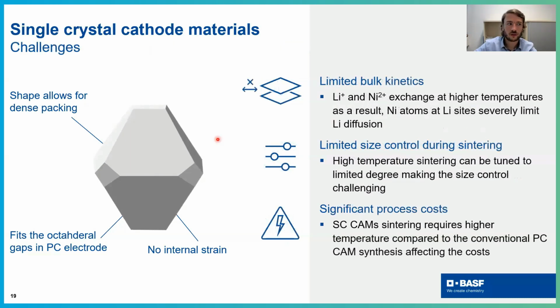Now, for sure, there are challenges associated with the synthesis of these materials. First of all, you are in the size of 3 to 5 microns typically, and this is huge compared to what lithium has to diffuse if you look at the conventional materials. In the polycrystalline materials, you have a crystallite size around 200 nanometers, and here you're around 5 microns. So it's an order of magnitude more. Lithium has to go through this bulk, and for sure you have limitations in terms of lithium diffusion.